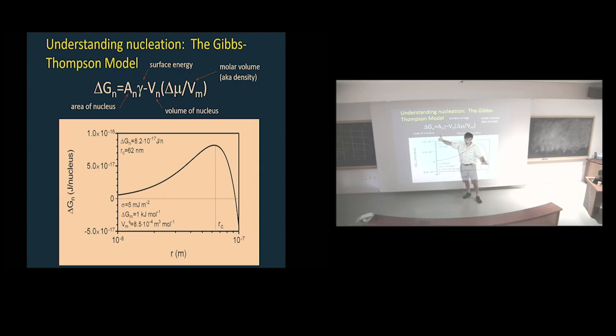It's like no good, right? You don't like interfaces. And this is the good part of the free energy, where you actually want to decrease the chemical potential. And that's a volume term, and that's just the volume of the nucleus. And here is your delta mu, and this is just the density of the material. So cool. If you mess with that equation a little bit, put in some unrealistic numbers, then you get a maximum as a function of the radius of that particular structure.